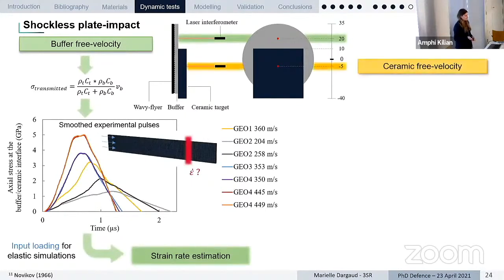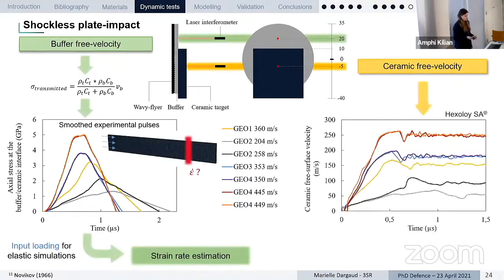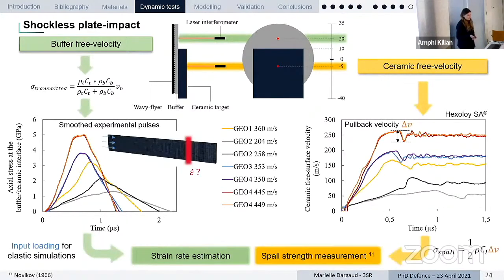In parallel, during the test, we use a second laser interferometer, which is capturing the free velocity at the rear face of the ceramic. Here you have the obtained profile for the free velocity, where we can see that we have a ramp loading, and then we have a drop of velocity. This is translating the failure of the material under the tensile loading. The drop in velocity is called the pullback velocity, and it can be used to measure the spall strength of the material using the numerical formula.